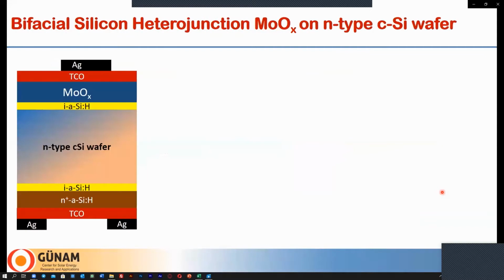Here, we applied hole selective molybdenum oxide in a large area bifacial silicon heterojunction solar cell. The N-type wafer is passivated with intrinsic amorphous silicon on both sides. The back surface field is formed by N plus amorphous silicon followed by TCO. On the front side, we have passivation with intrinsic layer followed by hole selective thermally evaporated molybdenum oxide, and then covered by ITO and low temperature screen printing and low temperature firing.